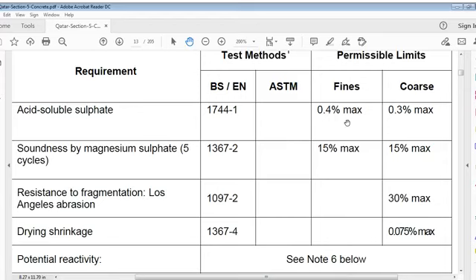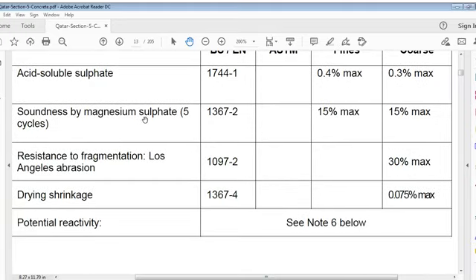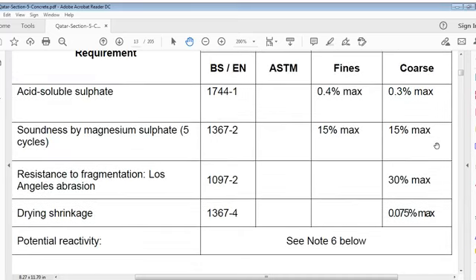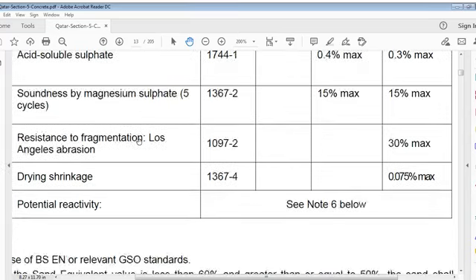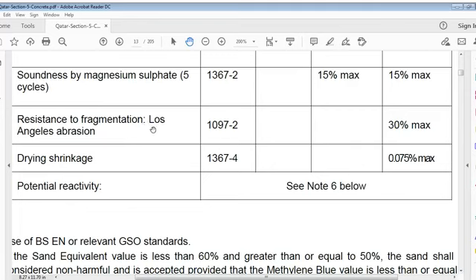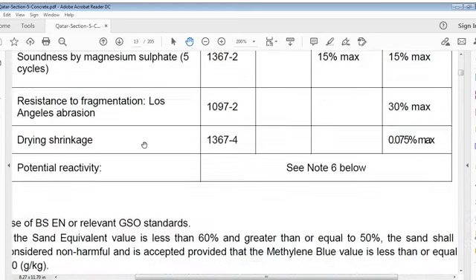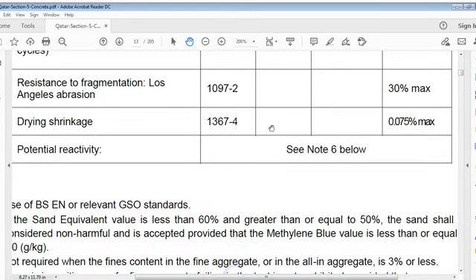Now the aggregates table continues, and we are saying acid soluble sulfate, 1744-1: 0.4% maximum and 0.3% maximum. Soundness by magnesium sulfate, 5 cycles, 1367-2: 15% maximum and 15% maximum. Resistance to fragmentation, Los Angeles abrasion, 1097-2: 30% maximum. Drying shrinkage, 1367-4: 0.075% maximum. Potential reactivity, see note 6 below.